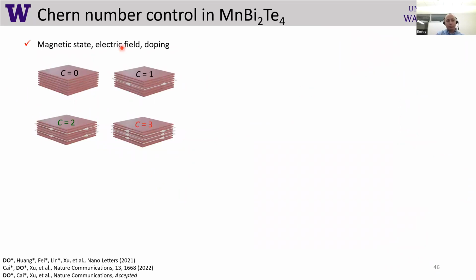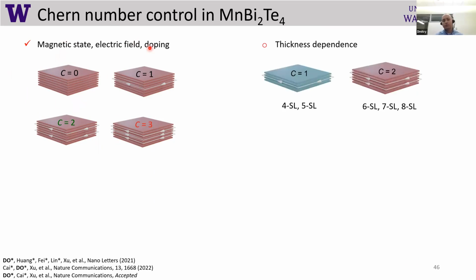So that's what I just showed you, that we can change these Chern numbers, change between them by these 3 means. What we also found, and that would be sort of the last part of my talk, is that we have a thickness dependence. And not only us saw that. In our case, when we have flakes or samples which are 4 layers or 5 layers thick, in most of the cases, we see only the Chern number 1 state. When we get thicker material, 6, 7, and 8 layers, we can get the Chern number 2 state as well. So essentially, those quantum Hall states are also there in addition to Chern number 1.